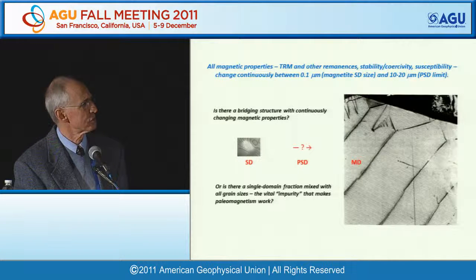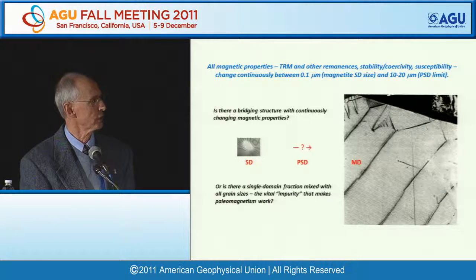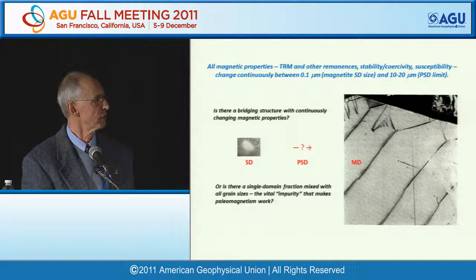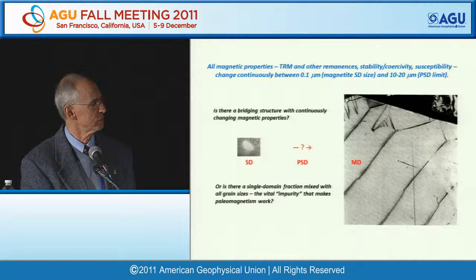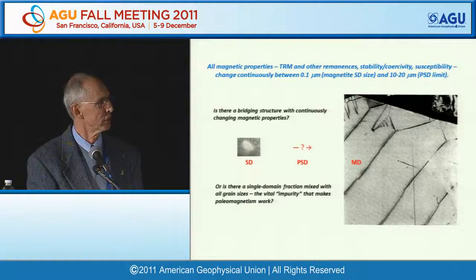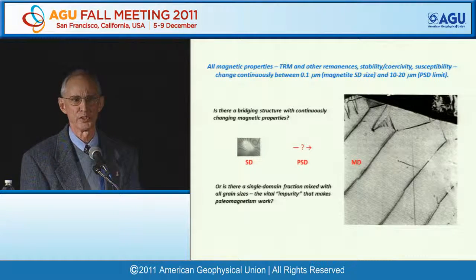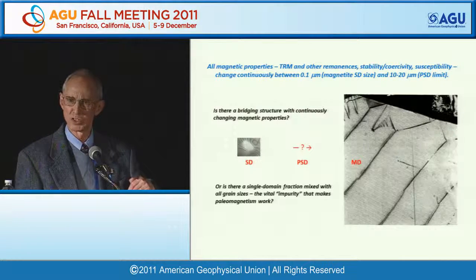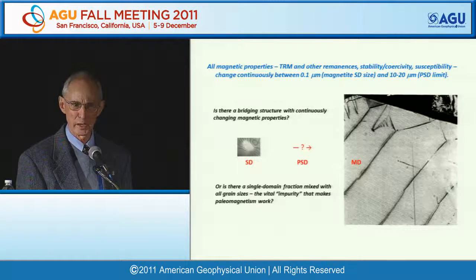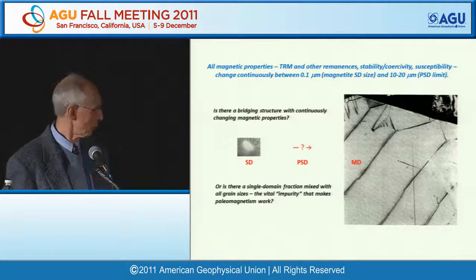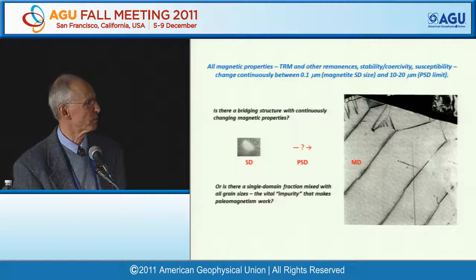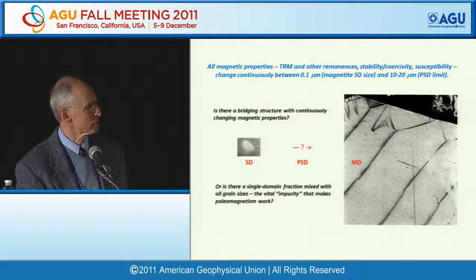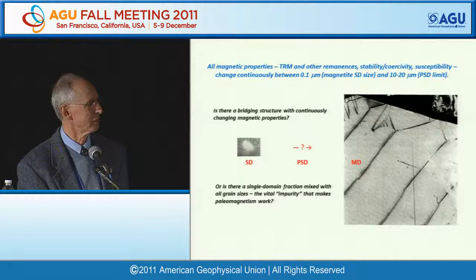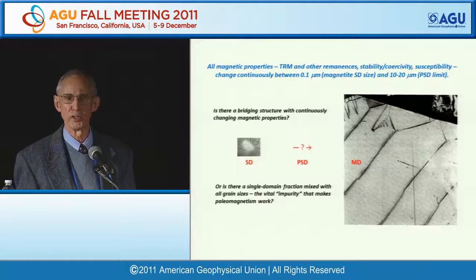Well, all magnetic properties, TRM, other remanences, stability, coercivity, susceptibility, we saw a few minutes ago, seem to change continuously between the magnetite single domain size and the upper PSD limit at 20 microns or so. So instead of the step-like change that one would expect between single domain properties and, say, the vortex state, instead we get a broad blend zone with continuous variation of properties. So what is the bridging structure, the domain structure that allows us to continuously change the magnetic properties between single domain and multi-domain? Question mark is there because I don't think we know.